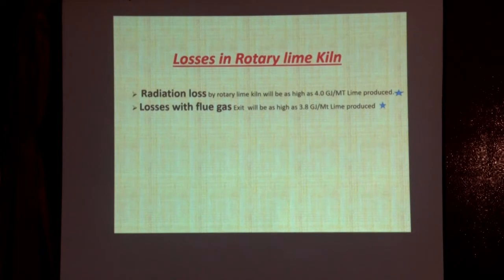Why is it happening so? There are huge radiation losses from the rotary lime kiln surface, which can be as high as 5,000 to 6,000 watt per square meter of surface area. There are also losses through the flue gas. It can be as high as 3.8 gigajoule per metric ton, which is actually more than the theoretical fuel requirement.